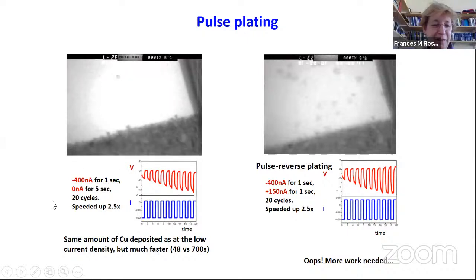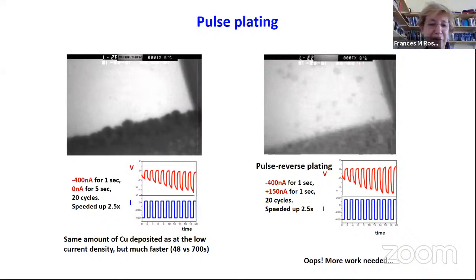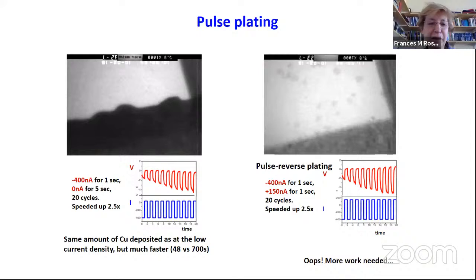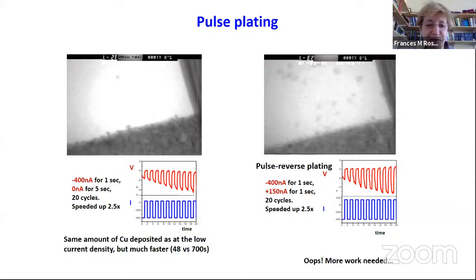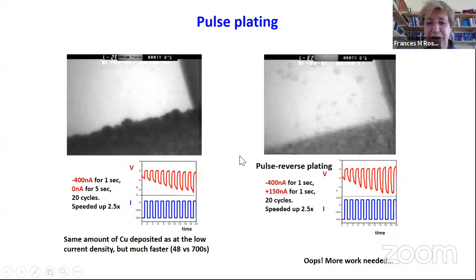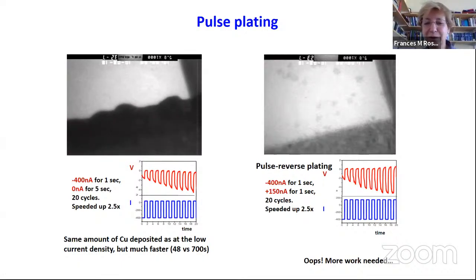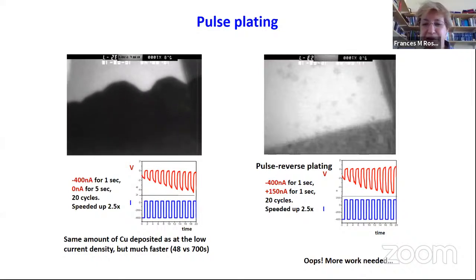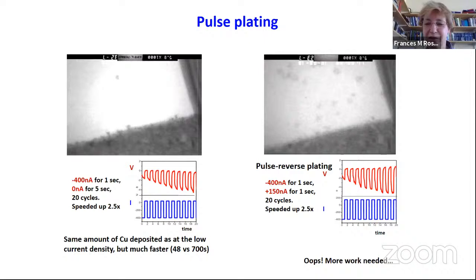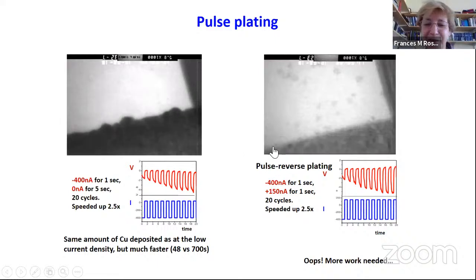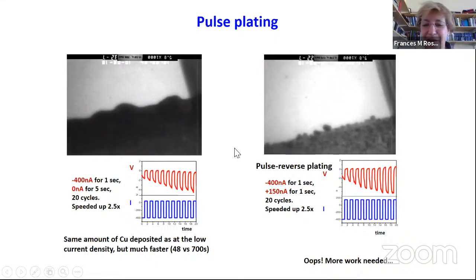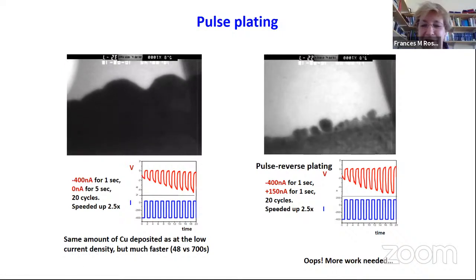because there's a lot of charging regimes where the current and voltage change quite dramatically with time. And so pulse plating is one of these very important processes where we stop depositing for a few moments to allow the diffusion fields to catch up. So you can track that in the TEM. But pulse reverse plating is the theory whereby you add some material and then you reverse the voltage. It knocks off the asperities, and then when you continue to add more material, maybe it grows flatter. So I want to show you how this works in the microscope. And you can see a pulse and a reverse on each cycle.